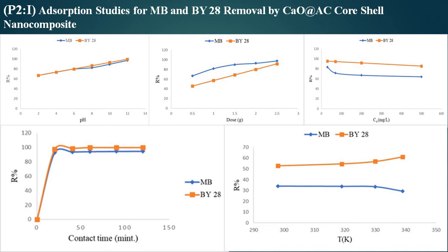In the case of initial concentration, we found that for the two dyes the removal efficiency decreased with increasing initial concentration. With contact time, we found the equilibrium time to be 30 minutes. With respect to the effect of temperature, we found that the BY dye adsorption increases with increasing temperature, but methylene blue decreases with increasing temperature, indicating that it is mainly physical adsorption more than chemical adsorption.